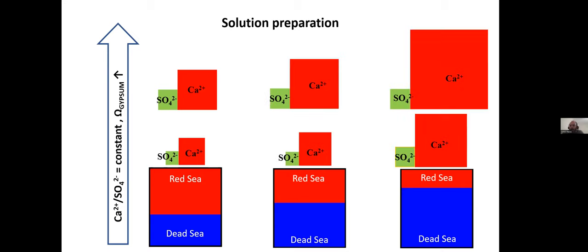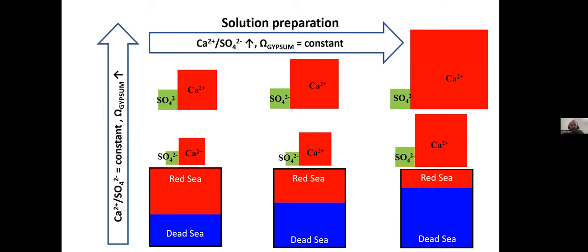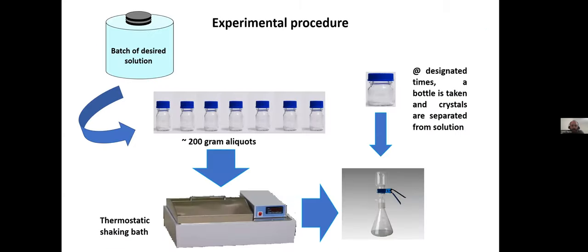I could also do it with other ratios between Dead Sea brine and Red Sea and get varying calcium to sulfate ratios, but a constant oversaturation. So I could look at how each one of these parameters impacts the system differently. So I did many batches of these brines. I divided them into aliquots and put them in a thermostatic bath to control the temperature. And at designated times, I would separate one bottle, separate the crystals from the solution, do chemical analysis, and look at the crystals.